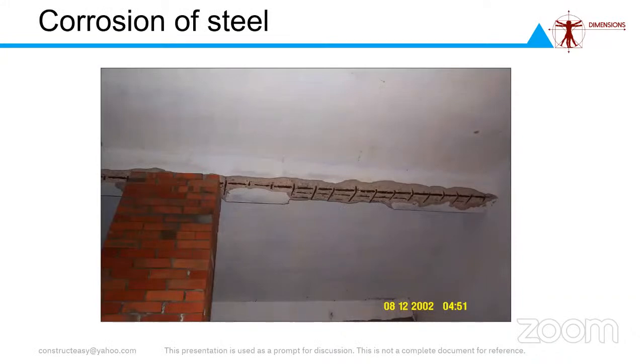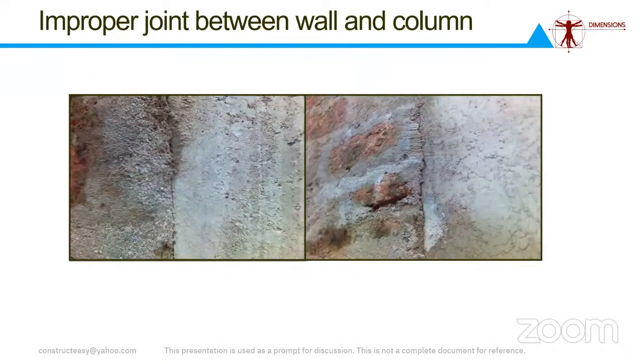And again, this is corrosion of steel, because you have been very careless in selecting the grade of steel, or you have been very careless in maintaining the uniformity of the quality of concrete along this member. So you will have the anodic and cathodic areas, and the steel starts corroding faster. Whenever you have different materials butting each other, as an RCC column and a brick wall, we don't give enough thought to the coefficient of thermal expansion of both the materials. You don't give enough thought to the shrinkage characteristics of the materials, and therefore you are bound to get a crack at the junction. This can be avoided by using suitable adhesives which are available in the market now. So this, to a certain extent, will withstand the tensile force which causes the cracks.